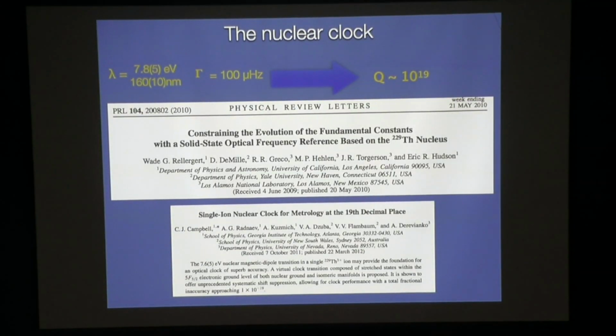We got involved. This is actually Dan's graduate student, Wade. We got involved many years ago, earlier than this, because we were trying to solve a problem of how do you find this transition. And what we landed on was that you could take this thorium-229, dope it into a solid state, high bandgap insulator, and not only drive this transition, but make a clock that has performance better than the definition of the second. It won't be as good as the ultimate, like trapped ion or trapped atom clocks, but it's better than the cesium standard, and it's in a little crystal that you could put in your pocket.